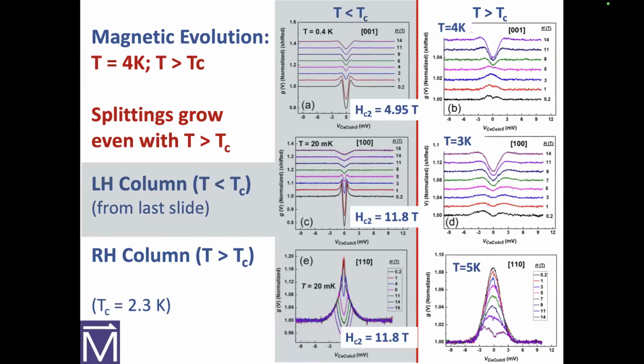Now, the grayed-out plots are the same ones I showed you before. Remember, these were all well below TC. Now we're going just above TC. TC is 2.3 degrees, and we have 3 degrees, 4 degrees, 5 degrees. And as we go up in field, we see the same kind of thing happening. We see something growing, something deepening, something splitting. Things are also happening in 110, but I'm not going to go into that.